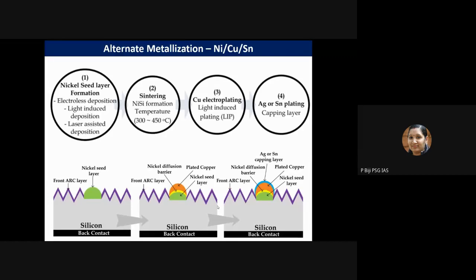Generally electroplating will be adopted, or there are many latest technologies like light-induced plating or electroless plating. There are many methods, and I prefer electroplating for copper. The fourth one is silver or tin. Silver is not necessary because the purpose is only to prevent the oxidation of copper, so we can prefer tin plating as a capping layer. That completes your metallization.